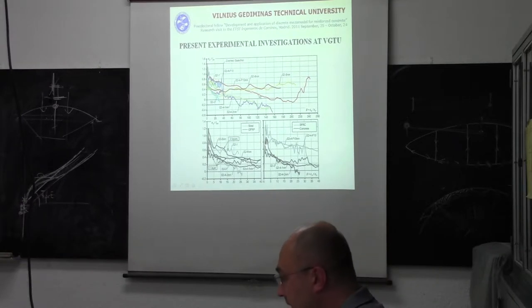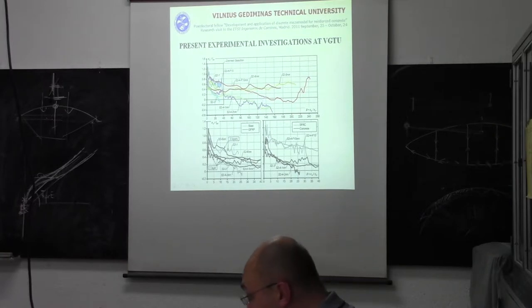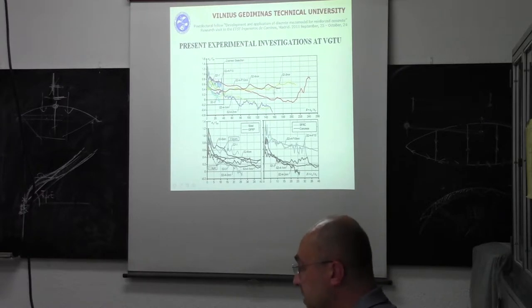I can comment. This red, this red, and this red diagram had fibers, and non-metallic reinforcement. This element, yellow, had three layers of non-metallic reinforcement. This, also red, had non-metallic reinforcement with the same depth to element height ratio. As we can see, this parameter is very important to consider for tension stiffening behavior.